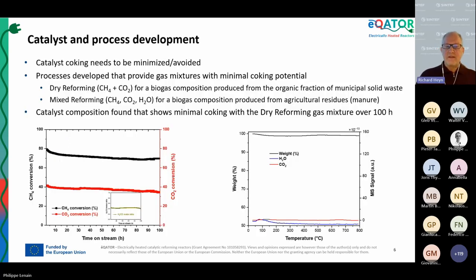So as I've mentioned, catalyst coking is very important. It needs to be minimized and avoided to the amount possible. And what we've done is we've developed two different processes to look at that will minimize our coking potential. So we have what we call a dry reforming process, which is simply methane and CO2, which starts from a biogas composition, which is like that you get from the making biogas from the organic fraction of municipal solid waste. We have a second process that we call the mixed reforming process, where water is added. We expect that to be a less risky proposition, but that mixed reforming process starts from biogas composition that is produced from agricultural residues.